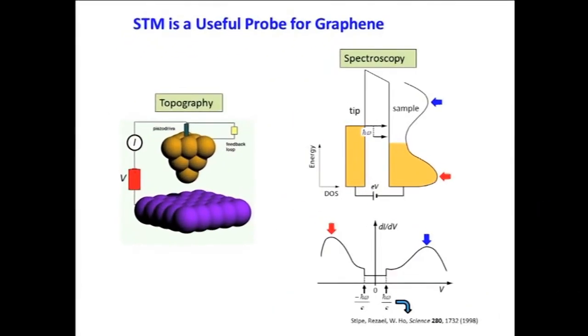So first, let's just start with discussing scanning tunneling microscopy as a technique for exploring small structures. A scanning tunneling microscope is a sharp metal needle, which we bring very close to a surface. We put a voltage between the needle and the surface, and we measure the tunnel current. And the rate at which these electrons tunnel from the tip to the surface is proportional to the electronic local density of states of the structure beneath the tip.